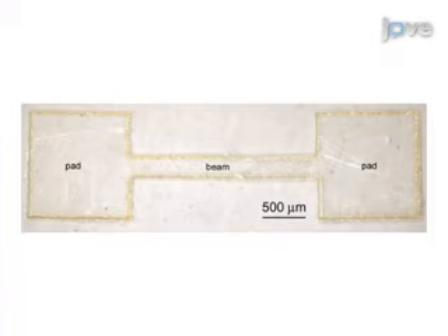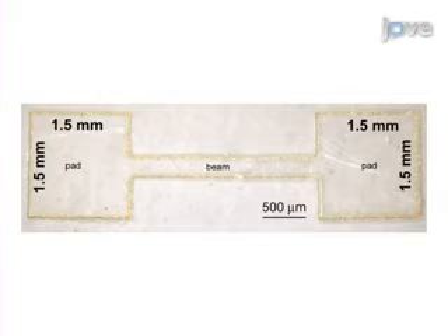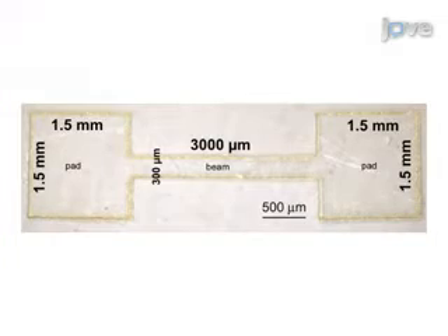The direct write laser micromachining parameters are set to a power of 0.5 watts, a speed of 56 millimeters per second, and 1000 pulses per inch. Machine the samples that will be used to establish environmental conditions, called setup samples, into dog bone-shaped structures with lateral pad dimensions of 1.5 millimeters by 1.5 millimeters and lateral beam dimensions of 300 micrometers by 3000 micrometers. The thickness matches that of the film throughout.